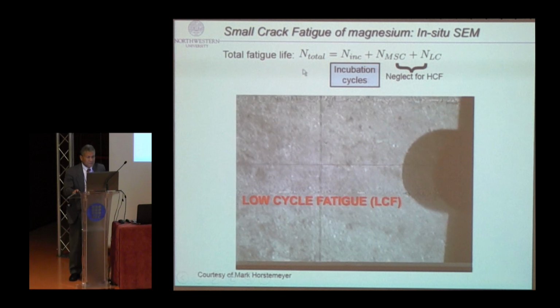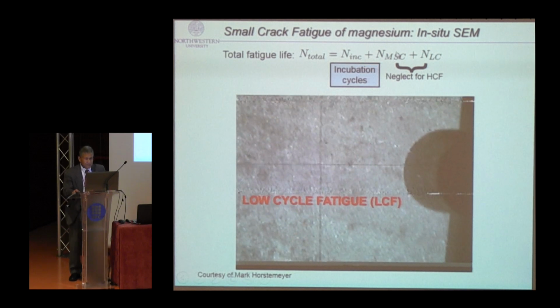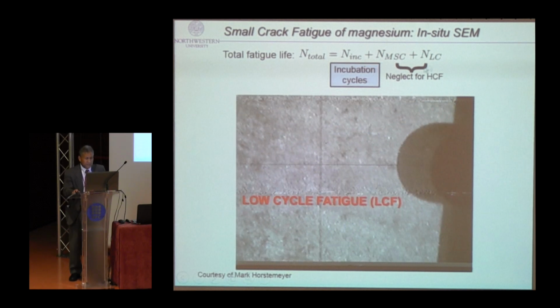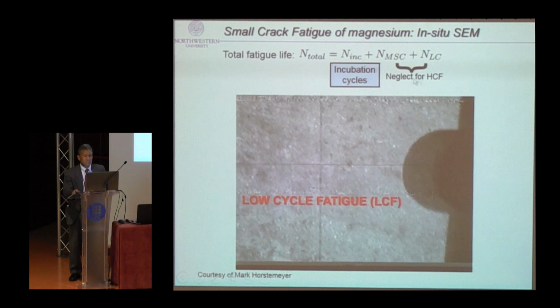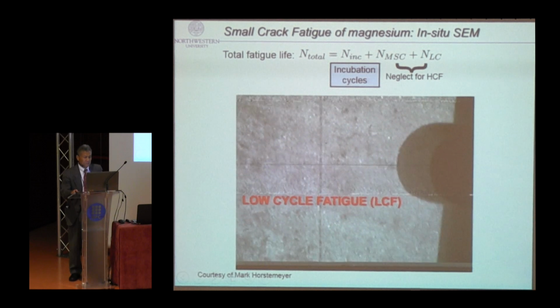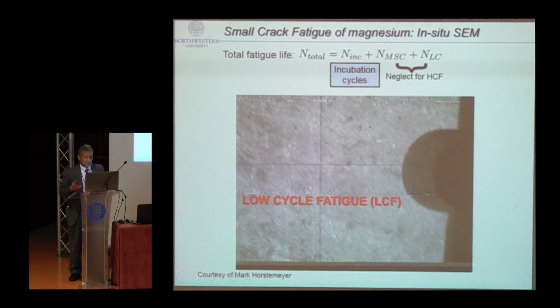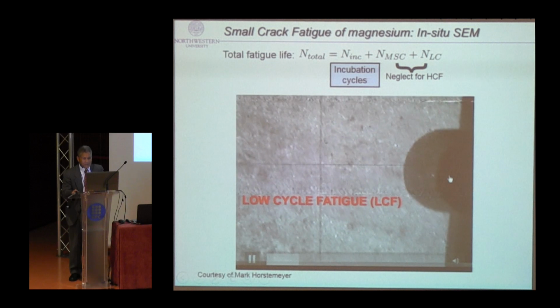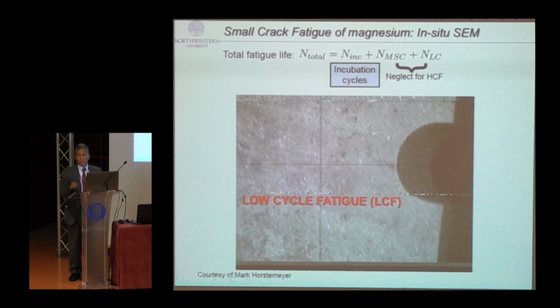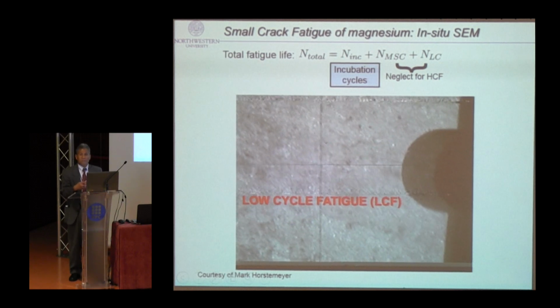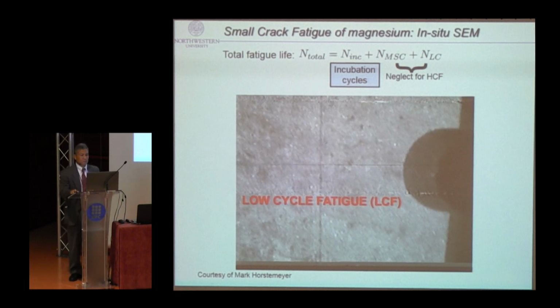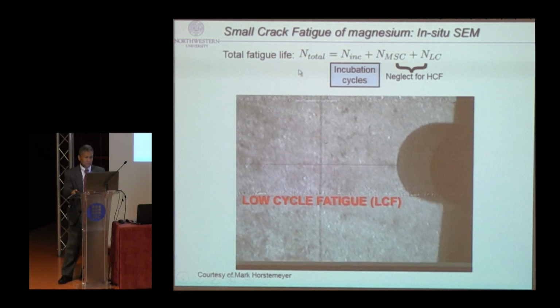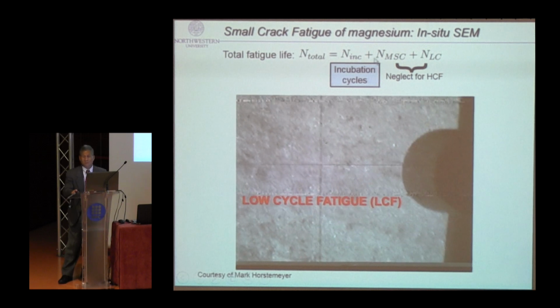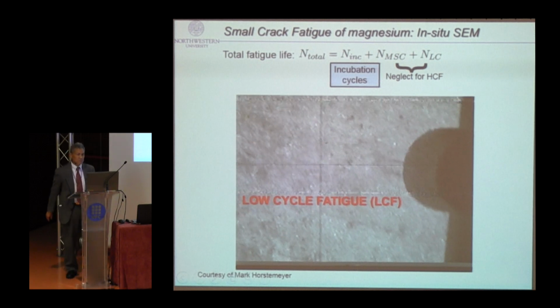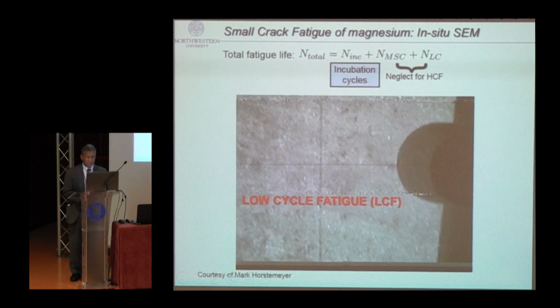The total fatigue life is governed by this equation. And most of what micromechanics or mechanics can do is for low cycle fatigue. And you can see how this one comes about. Usually you assume a crack, and you see how it goes, but mostly it's like void growth and coalescence. It's a pretty well-known way to look at a problem. But we want to look for the incubation cycle. That means we're focusing on high cycle fatigue in this particular problem.